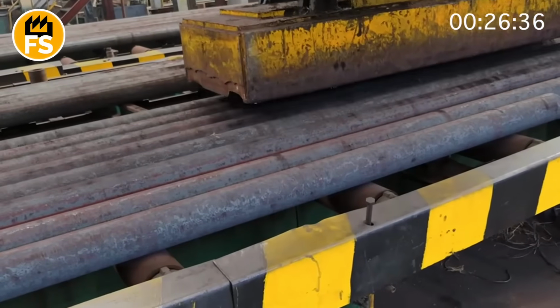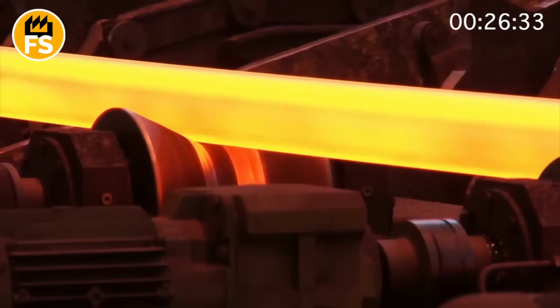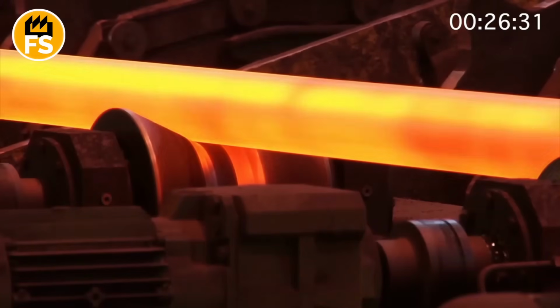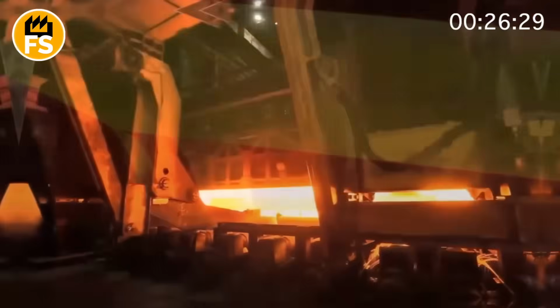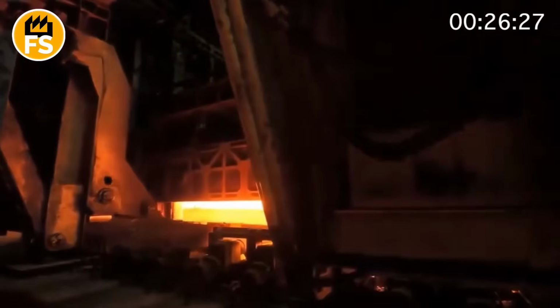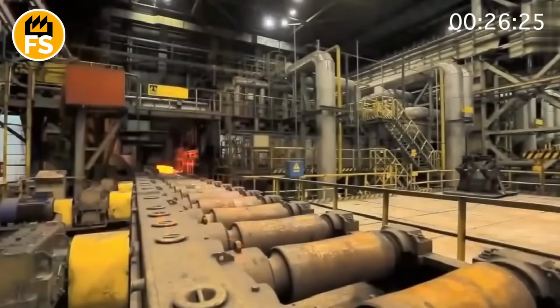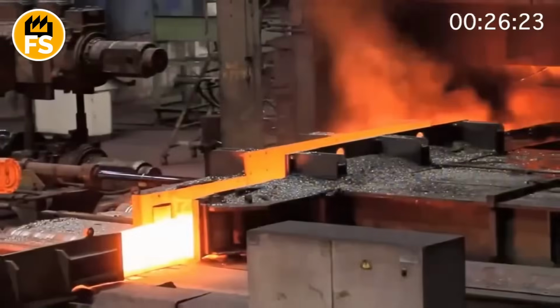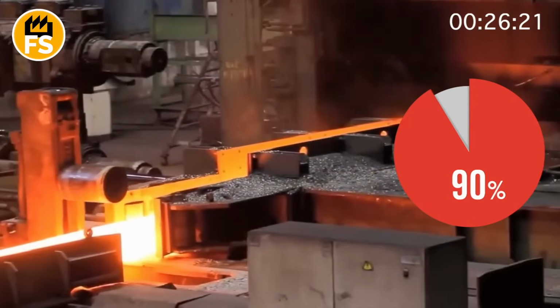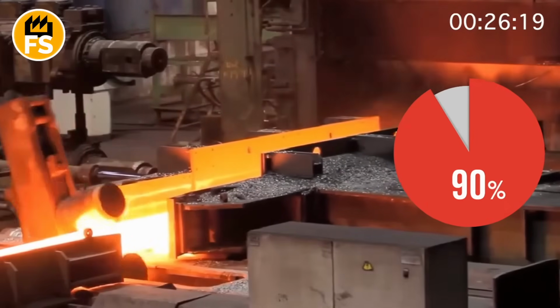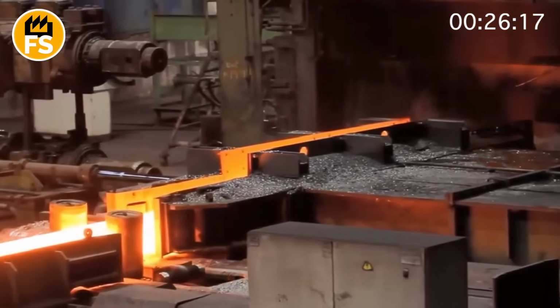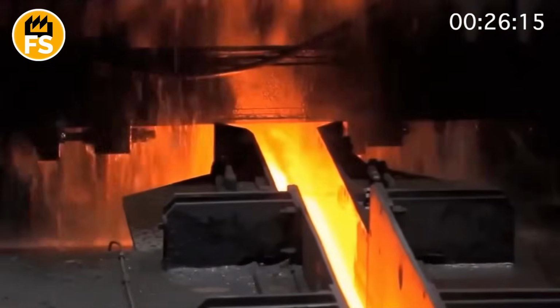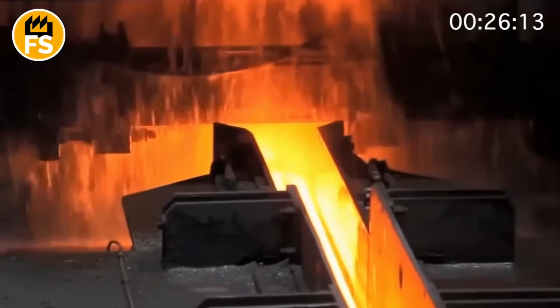Defective billets are sent to an electric furnace with a temperature of 2,900 degrees Fahrenheit, where the steel becomes liquid again. All the post-melting slag is used for road construction. 90% of defects are detected during the ultrasonic diagnostic stage. It's like finding a needle in a haystack in 10 seconds. The chemical analysis takes 17 seconds, faster than you order coffee at Starbucks.